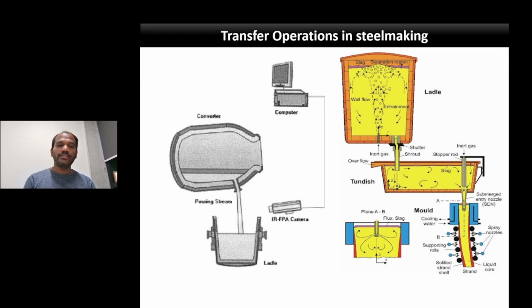However, the disadvantage is the BOF slag, which is actually carrying over into the ladle, has a lot of excess oxygen that comes from reducible oxides like FeO, MnO, P2O5. So there is always a trade-off, that how much amount of slag carryover is to be allowed, and it should be as little as possible for several critical steels that demand slag-free tapping.